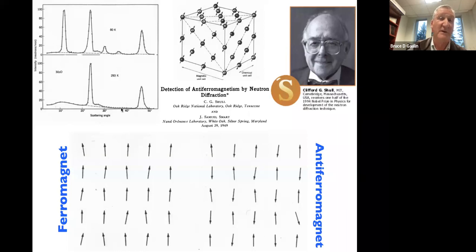It's a powder diffraction experiment that you see in the top corner here on the left, where as you cool the system down from room temperature to liquid nitrogen temperature, a series of extra Bragg peaks appear. In due course, those were interpreted as arising from the ordering of the dipole magnetic moments associated with manganese. Anyway, all of that only happened in 1949, as a consequence of the development of nuclear reactors and such. But 1949 was the point where you could really study antiferromagnets in a serious way, at least with these relatively simple ordered states.